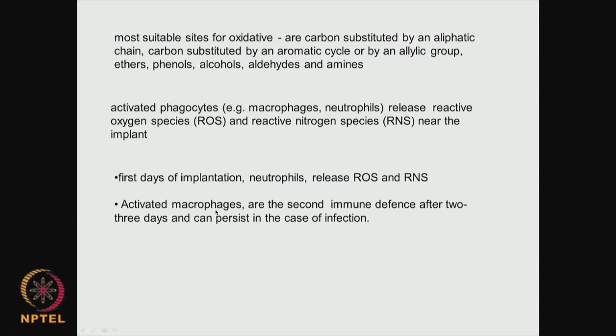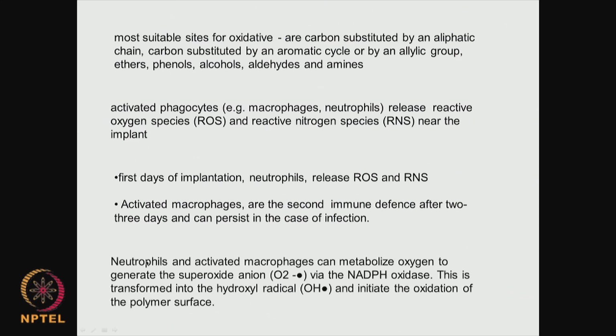Now, later on the activated macrophages, they are the second line of immune defense, which happens after 2-3 days in case there is an infection. So, as soon as an implant is placed inside the body, these neutrophils release ROS and RNS, so they can start oxidizing your implant. Then after some time you have activated macrophages, they are the immune defense system, they also start releasing these reactive oxygen, reactive nitrogen species. So, neutrophils and activated macrophages can metabolize oxygen to generate the superoxide anion via the NADPH oxidase, which is transformed into the hydroxyl radical and initiate the oxidation of the polymer surface.